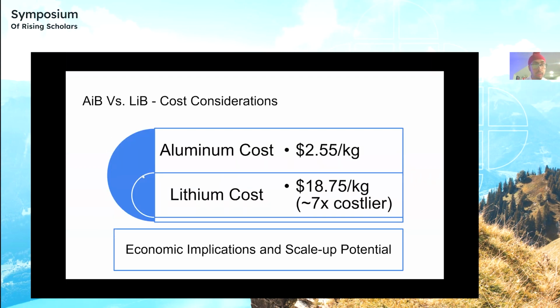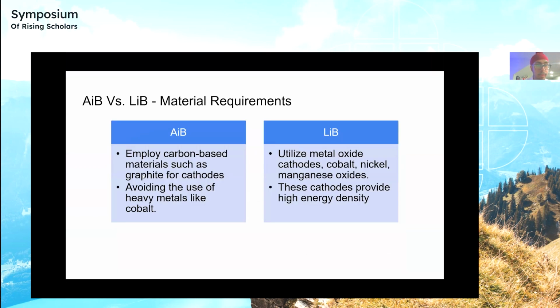All right, some cost considerations to keep in mind. Aluminum costs $2.55 per kg, whereas lithium costs $18.75 per kg, which is almost 7 times costlier. So this has a lot of economic implications and problems in the scale-up potential. So the material requirement. Aluminum-ion batteries employ carbon-based materials such as graphite for cathodes, and they don't use heavy metals like cobalt, which are not sustainable. On the other hand, lithium-ion batteries utilize metal oxide cathodes, such as cobalt, nickel, and manganese oxide.